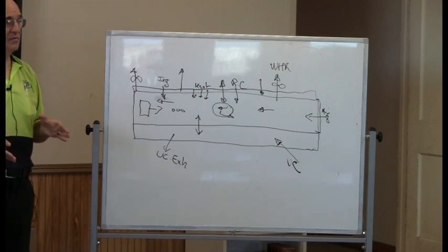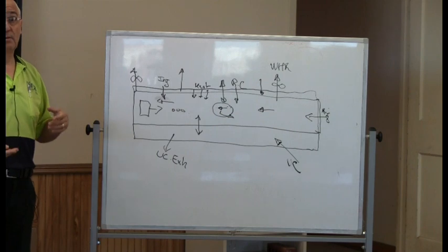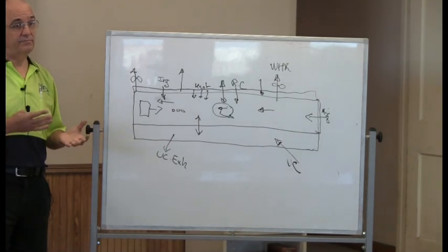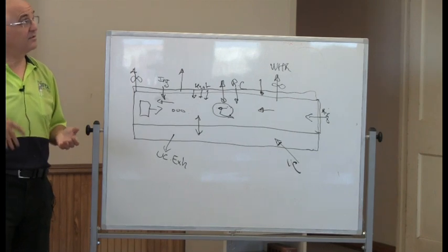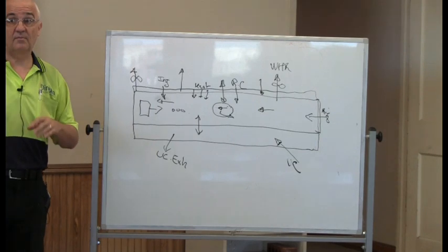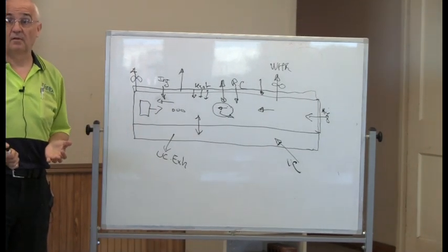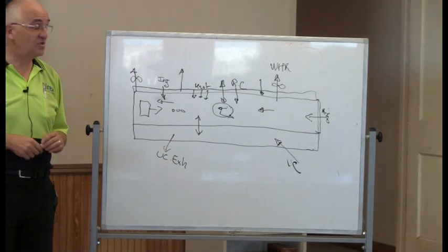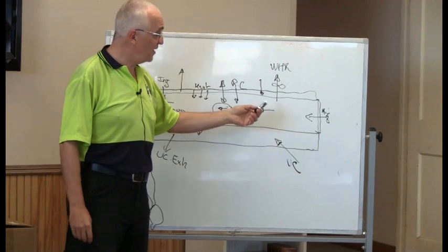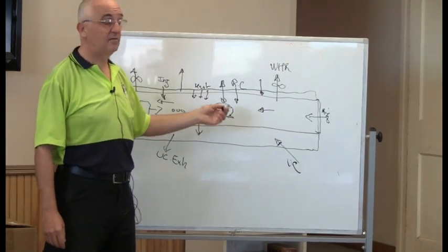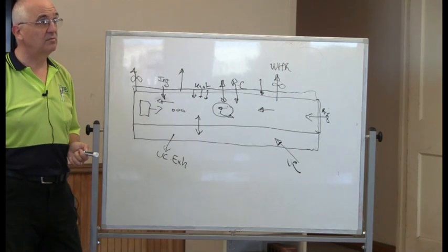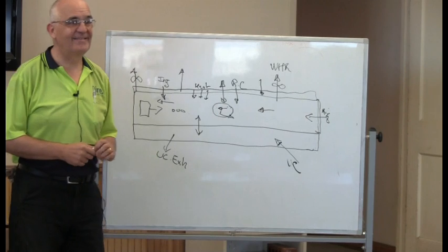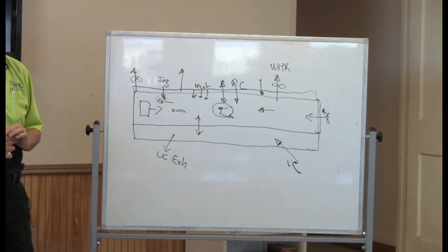The next step is burner adjustment and getting the burner with the power, with the flame temperature. In the preheat, yeah, you may want a flame at lower temperature, but you still need to be reasonable with that, because when you talk about 100-200% excess air on a burner, and I'm not saying that's the case here, but I've seen places where people put 200% excess air, well, it's very, very costly in terms of energy. So if I have another means, which is to use the air and the energy inside the kiln and move it properly, then my kiln is much more efficient. Yes? Do we agree on that? Yes. You've already paid for that energy. Yes.